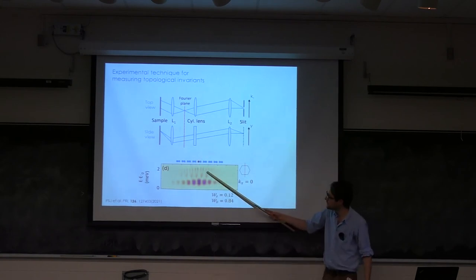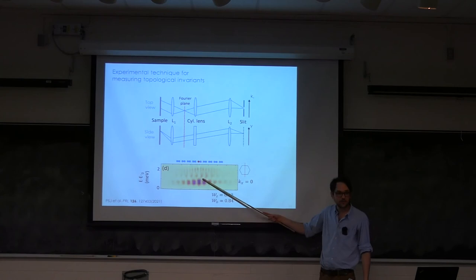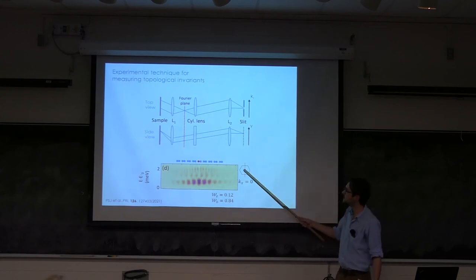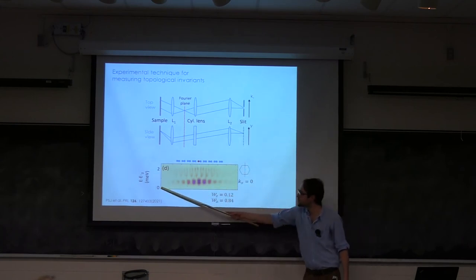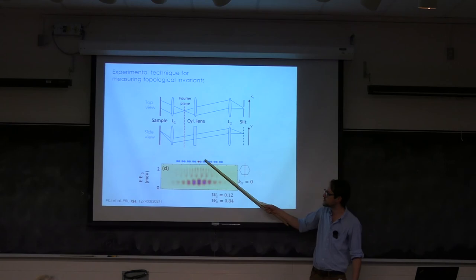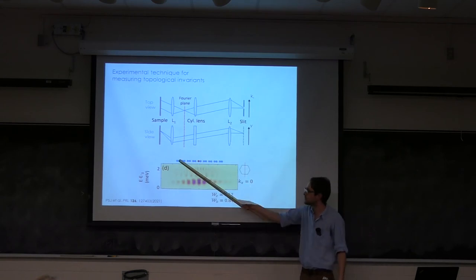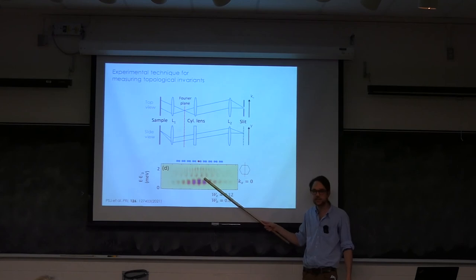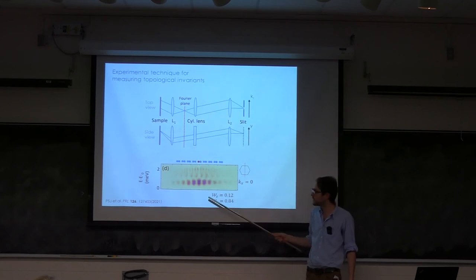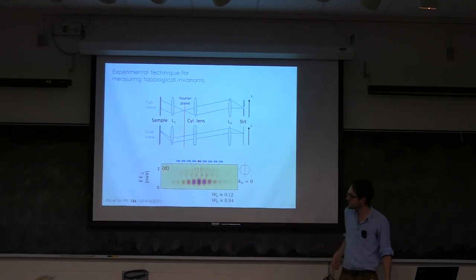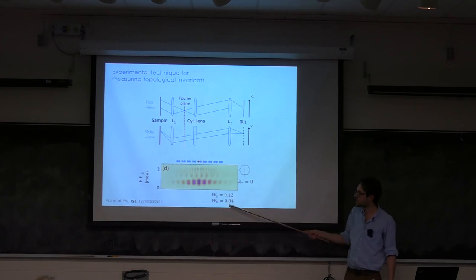And so what I'm showing here, it's not SSH, this is really a spectrum taken from our system for lattices of graphene, where we have positioned this slit in order to select this k equals zero component. And you see as a function of position, I'm just positioning artificial atoms here just to give you an intuition of where we are. And we really have these two bands, just like an SSH, a bonding band and an anti-bonding band. And now we can compute these chiral displacements. And we don't exactly go to 0 and 1. I'll come back to this in just a few seconds. But we really have something that is closer to 0 and closer to 1.